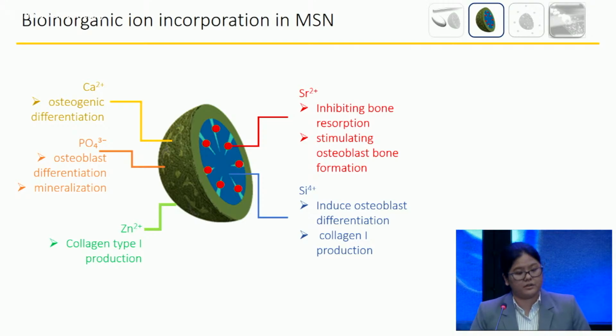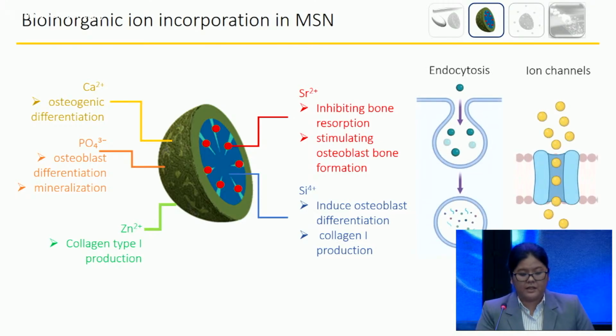In this project, we use a mesoporous silica nanoparticle loaded with a strontium ion with or without calcium phosphate coating to deliver single or multiple ions to the cells. The additional benefit of the calcium phosphate coating is that it is pH responsive, where we only observe the ion release at a low pH, such as that found in the cell vesicle during the cell uptake of the mesoporous silica nanoparticle. This process is called endocytosis. Since the ion is also taken up via the ion channel, we also want to investigate the effectiveness comparatively to each other.